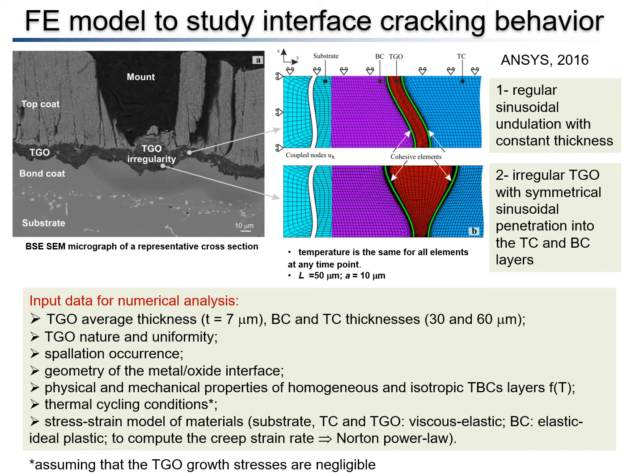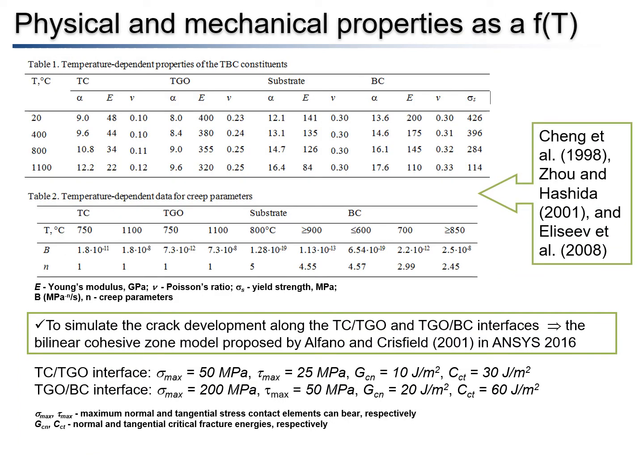The input data for numerical analysis are listed here. You can see different parameters. Thermomechanical properties as a function of temperature and creep parameters of different TBC components were extracted from corresponding literature and provided by our industrial partners. To simulate the crack development along two interfaces, the bilinear cohesive zone model was used.